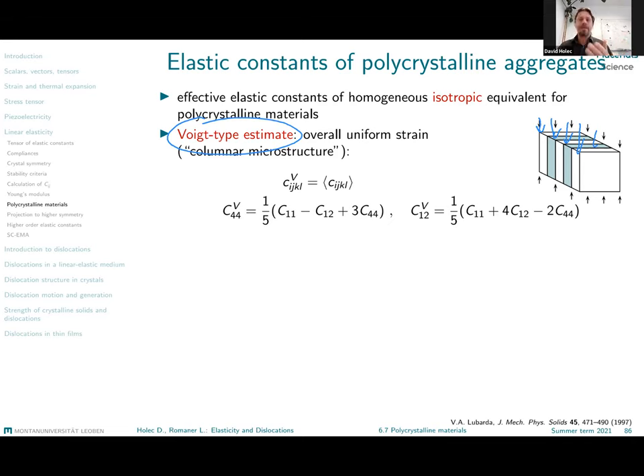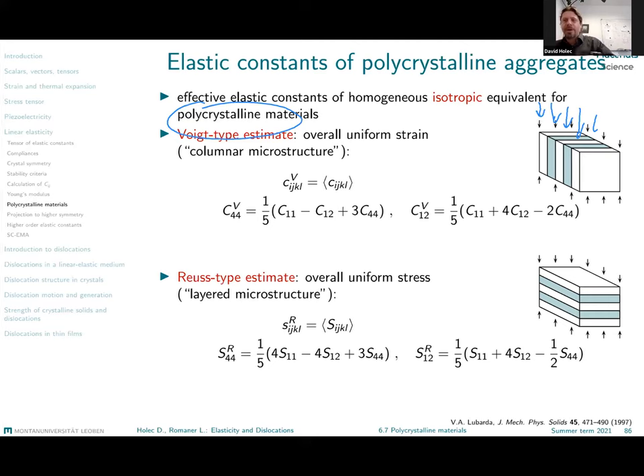This average comes from the fact that we deal here with linear elasticity. I can come also to the other extreme, where now all my grains experience the same stress, independent of how they are oriented. But again, using the same argument as before, they do not have the same strain. They cannot, because they are not elastically isotropic. And so each of these grains would be differently deformed, some of them more, some of them less. And the macroscopic strain that I measure for this aggregate of grains will be an ensemble average of all of those. So for the Voigt and Reuss estimates, we indeed talk about the uniform strain or uniform stress over the whole ensemble.